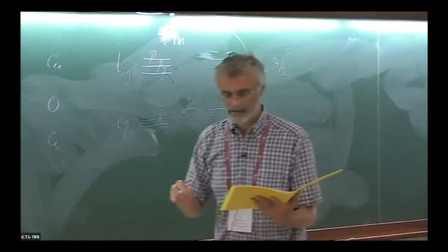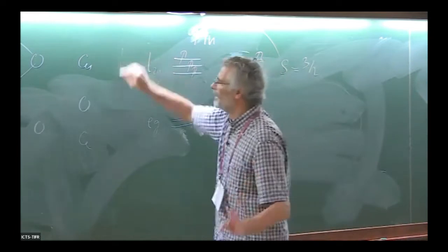Yes. Right. This is the reverse order of the orbital energy diagram. What I mean to say is, the T2G orbitals have lesser repulsion. They experience lesser repulsion from the oxygens which are sitting along the XYZ direction, so their energies are lower. And the EG orbitals experience more repulsion, so their energies are higher. That is the correct picture in the manganese case. That depends on if the octahedron is elongated or not, that's right. Okay. Yes, sorry. Okay, so this is not an energy axis.